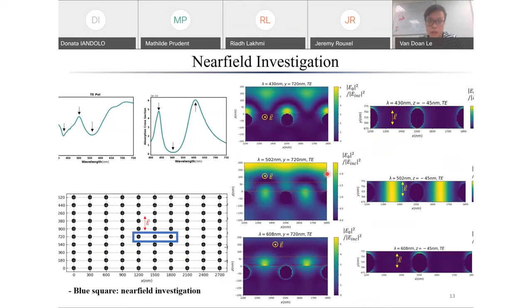And in the XY plane you see here the field distribution is passed along by the grating, so it is the indication of Rayleigh anomaly. And at the third point, at the peak of absorption, you see the field distributed around this red square I point out here, which represents the high index layer, which means that the field is trapped in the layer, and we call it guided mode resonance. Because in the XY plane you see the intensity of the localized surface resonance is really huge, it means that the diffractive wave is coupled with localized surface resonance, and somehow it also couples with the waveguide modes of the high index layer. So it leads to the guided mode resonance.